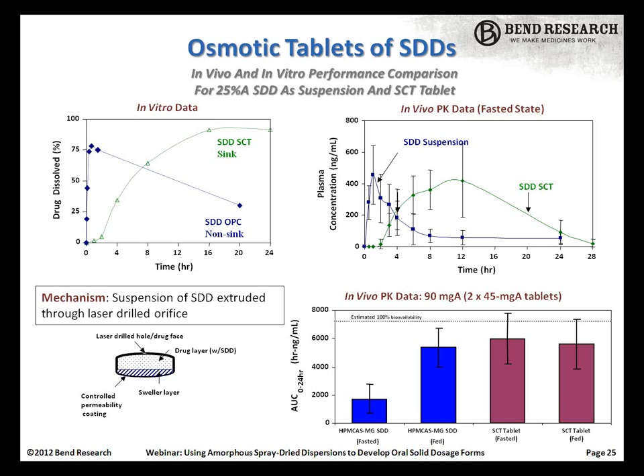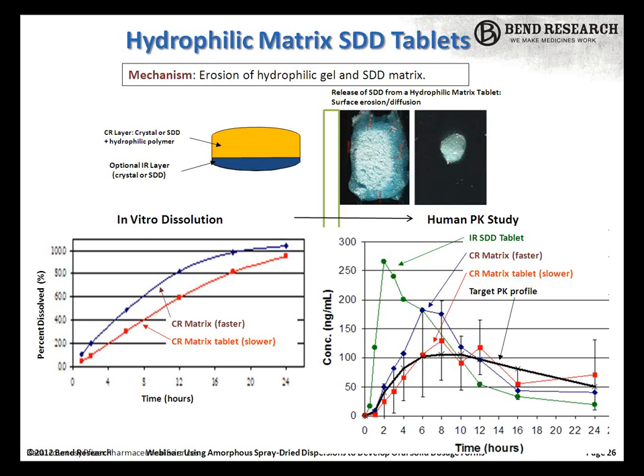We can also take the spray-dried polymers and incorporate them into a standard hydrophilic gel matrix tablet, commonly HPMC, but we can also put these in PEO or HPC or other hydrophilic matrices. Probably the key thing to note, as opposed to a crystalline drug, is that the dispersion itself is a polymer that has some viscosity, and there tends to be some interaction of this polymer with the hydrophilic matrix, and it tends to form a fairly robust gel. So what we end up with is the equivalent of a gel matrix tablet that has a poorly soluble compound. Of course, the drug is poorly soluble, but even using these polymers does not render it a different mechanism. So it does maintain this erosion mechanism.